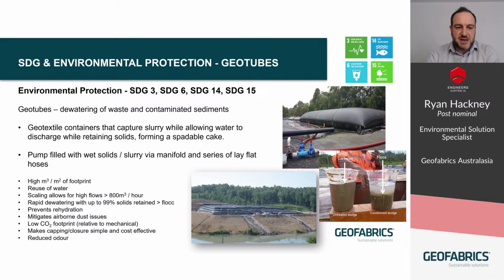Moving on to geotubes. So geotubes, we've seen examples of those previously. They are used to dewater waste and contaminated sediments. They're geotextile containers, and they capture slurry while they allow water to discharge out of the pores, and the solids remain within the tube, and the water is discharged, and the whole intention is to end up with a spadable cake within the tube. The geotubes are pumped with the wet slurries via a manifold and a series of lay flat hoses, and we typically incorporate flocculants and coagulants into this process before the slurry gets into the tube, and that helps to more quickly evacuate the water out of the pore space.